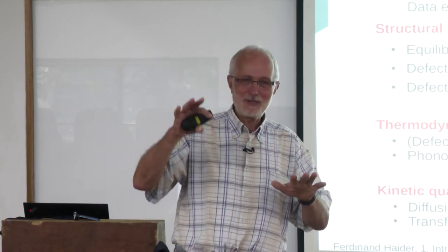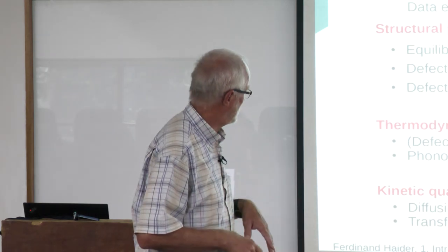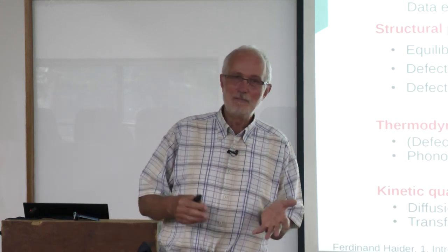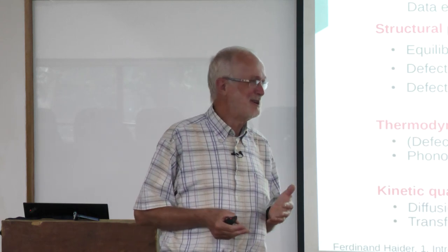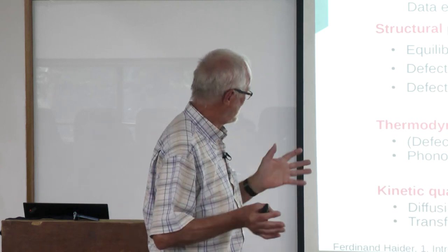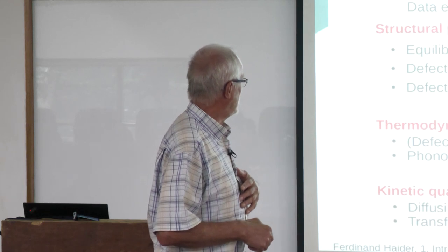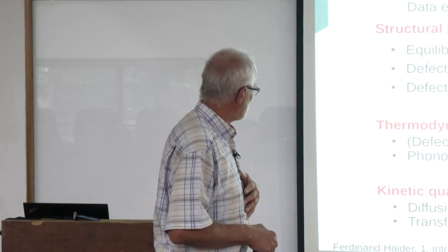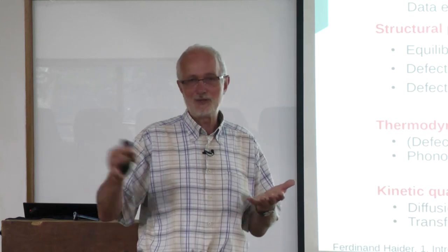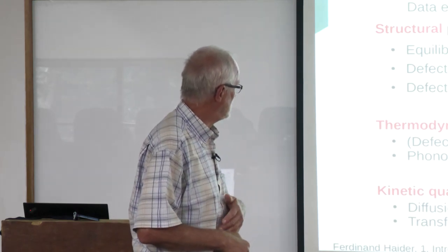If you raise the temperature, as you saw, you can change the stability of phases. Everybody knows, and we will come to this later on. What controls this are the free energies. By applying certain tricks we will learn here, you can obtain free energies. And free energy is something different than energy. As I said, this will be part of the next lecture. What you also get, I call kinetic properties. How much energy is required to shift an atom to a neighboring place, so the activation energy for diffusion. These are also very important quantities you can get out of it.